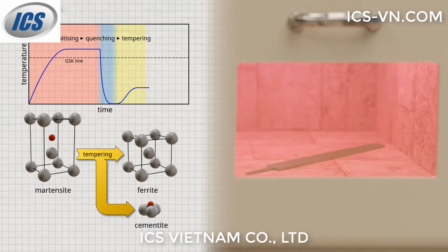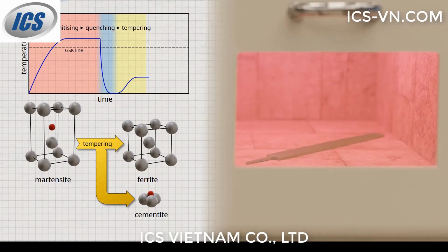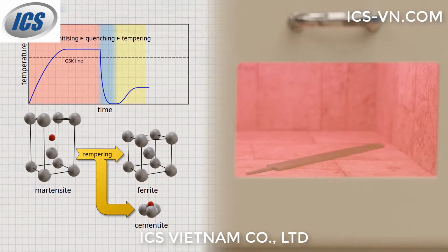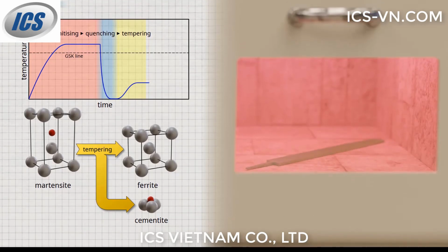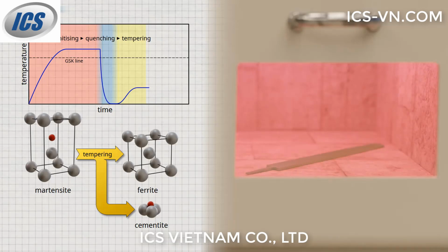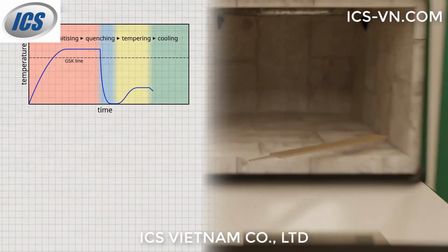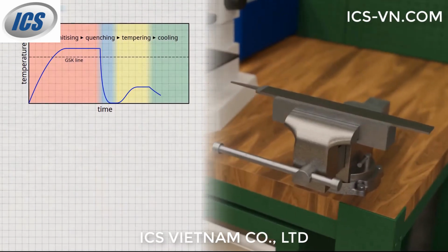Due to the increased temperatures during tempering, the carbon atoms that are forcibly dissolved in the martensite can partially diffuse out again. As a result, the tetragonal martensite recedes and the lattice distortion is partially reduced. Hardness and strength are somewhat reduced, but the steel gains considerable toughness. After tempering, the steel is usually cooled slowly in air.